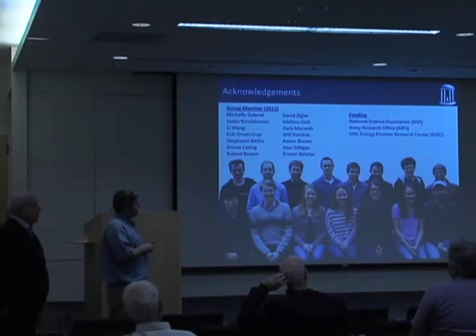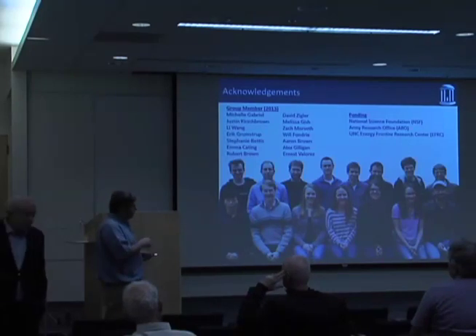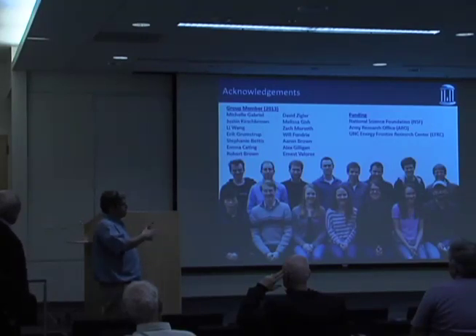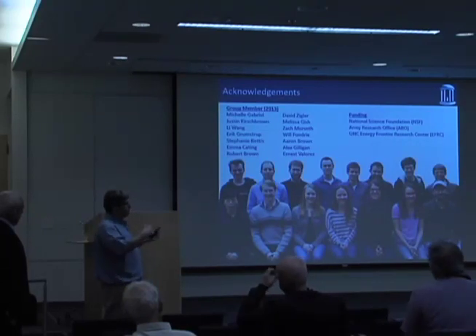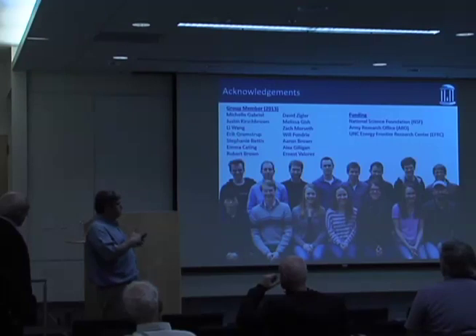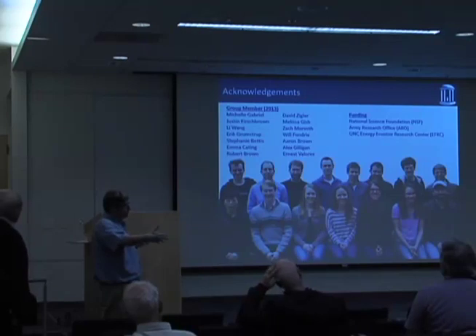They're sitting on glass or quartz substrates in air under ambient conditions. So we have looked at a little bit. We've now started, with Jim's group, to look at different passivation. They can grow the nanowires and you could have a native oxide on it, or they could grow a thermal oxide on it, or they could do hydrogen annealing and different surface treatments. We have started comparing different surface treatments, and there is a difference in the kinetics when you do that. The thermal oxide gives you longer lived carriers than the native oxide and so on. But we haven't done that systematically yet, and we're going to start doing that.